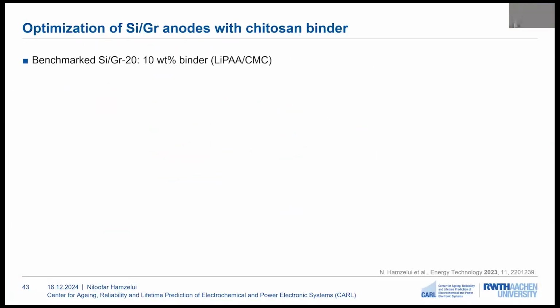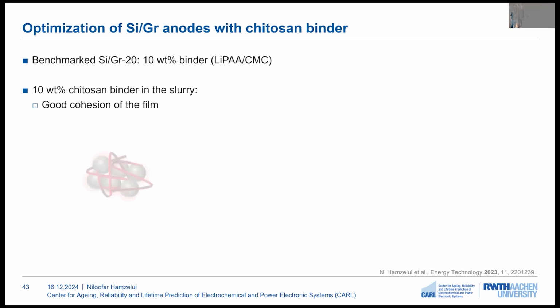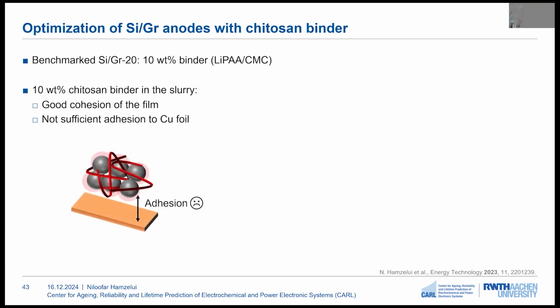Then the binders were implemented into the silicon graphite electrode using the benchmark electrode, which was discussed in the previous chapter. And in that electrode, a 10-weight% binder of lithium polyacrylic acid and CMC was used. So the same formulation was done by using 10-weight% chitosan binder in the slurry. And these electrodes showed a good cohesion of the film, but there was not sufficient adhesion to the copper current collector, and after drying, the films were delaminated from the copper current collector.